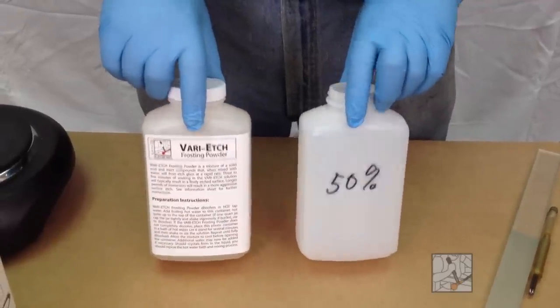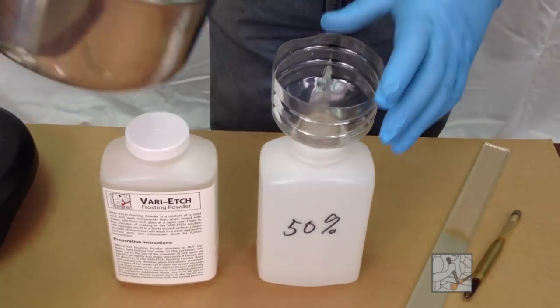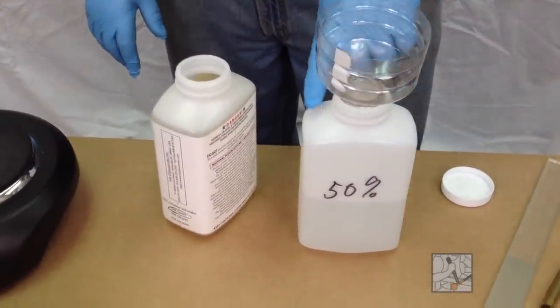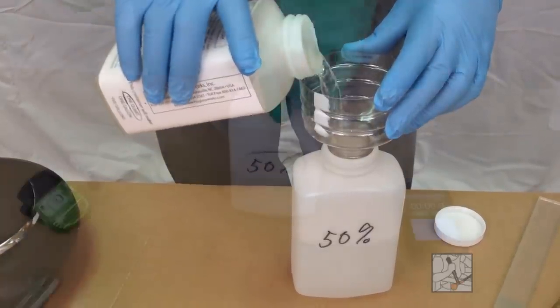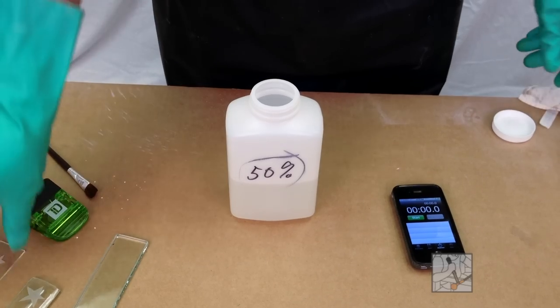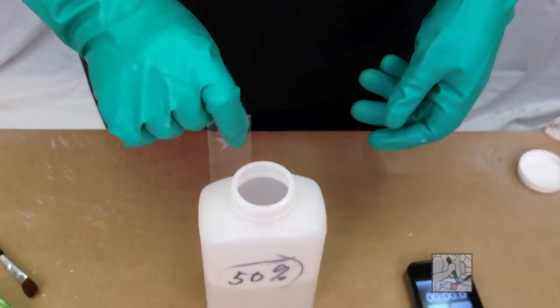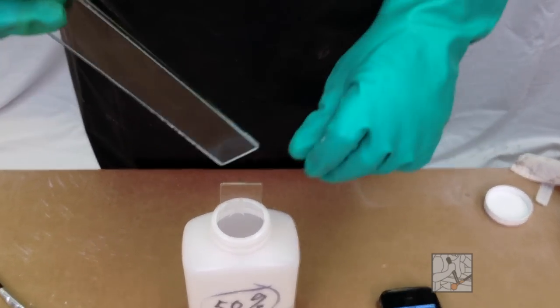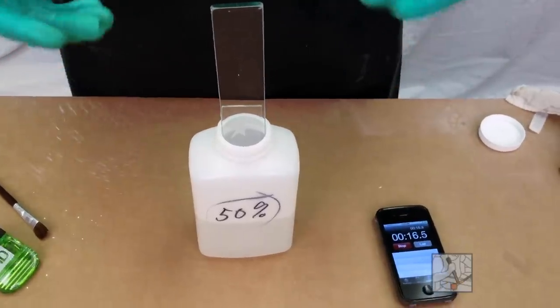You can change the concentration of the acid bath and get different effects. What I'm going to do is add 50% of acid and 50% of water. I'm going to add water first, always add acid to water, never the other way around. And again using the funnel, pouring in up to the line about 50% or to the one line of water. Now having made our 50% solution, I'm going to open that up. I'm going to etch three different pieces of glass. This is a piece of single strength window glass. I'm going to place that in for four and a half minutes. At the same time, I'm going to put in a piece of quarter inch float plate glass, which is a quarter inch float. So one side of that glass has tin on it. I'm going to show you what happens with the tin as it affected by the acid.